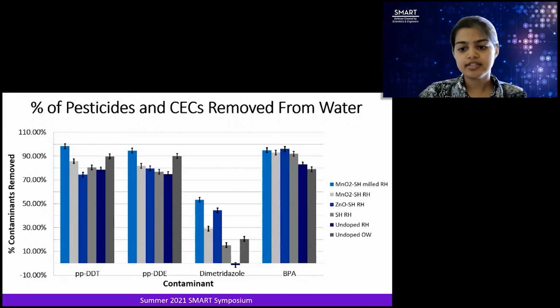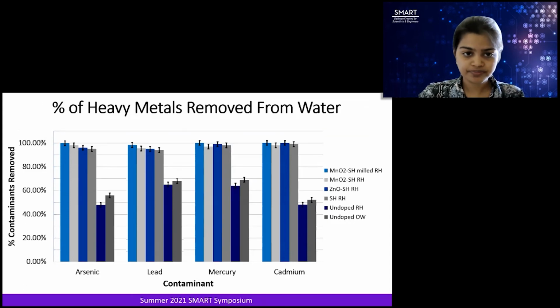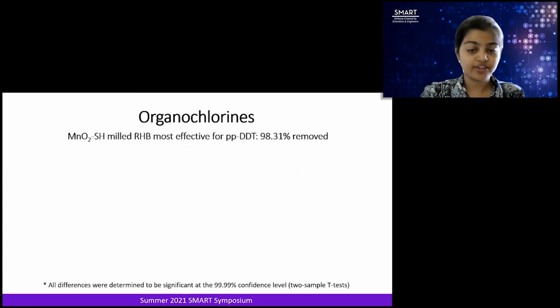Here you can see my results, and as you can see here, manganese oxide thiol-doped milled rice husk biochar appears to be significantly more effective than other biochar types at contaminant sequestration. Again, for heavy metals, the same trend applies. Manganese oxide thiol-doped milled rice husk biochar appears to be very effective.